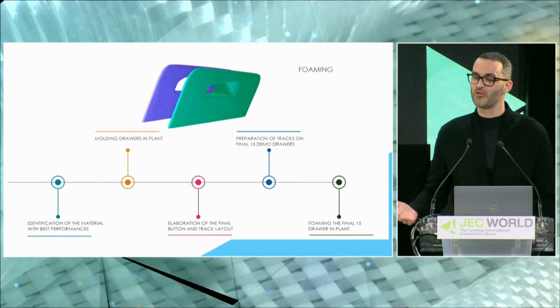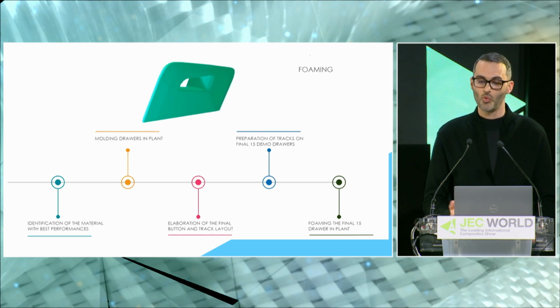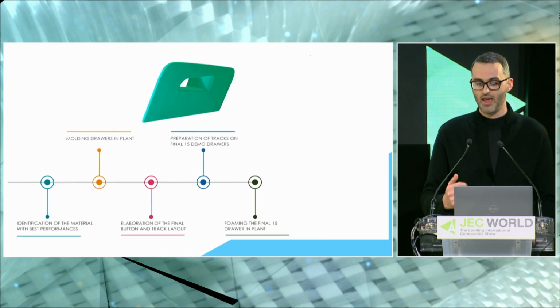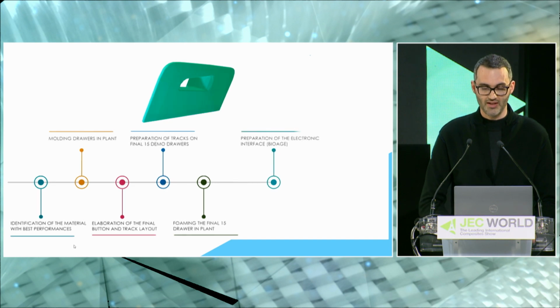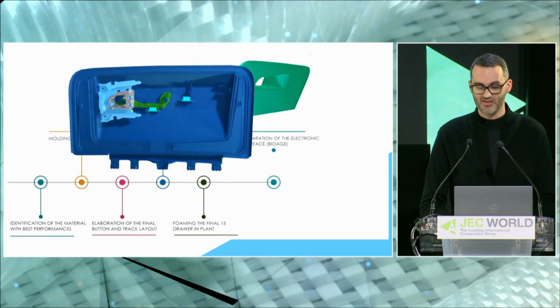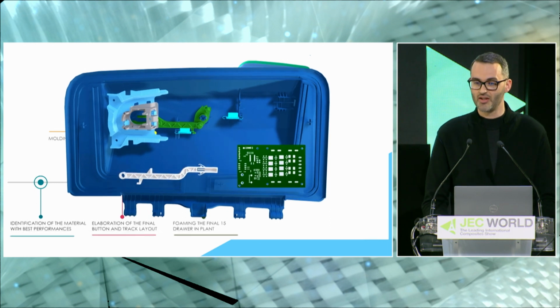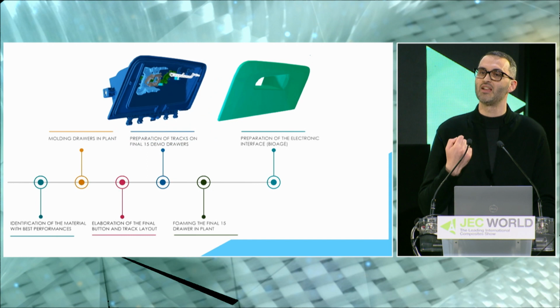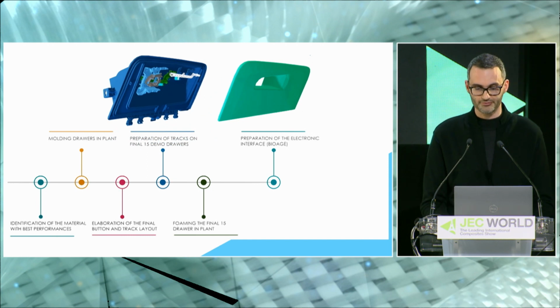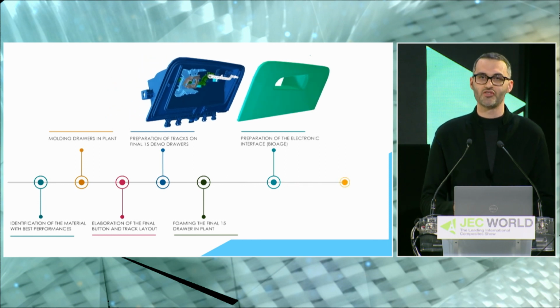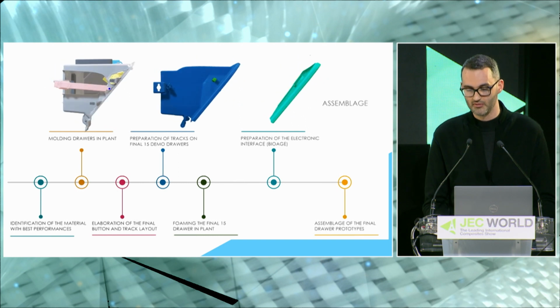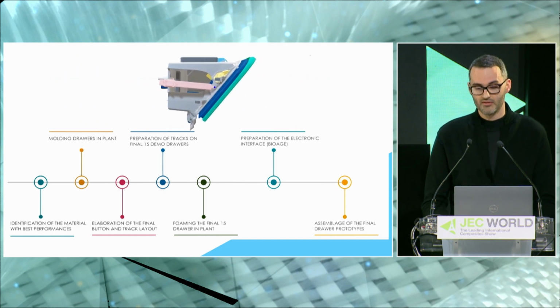And then we are moving to the other manufacturing phases that are typically performed on traditional materials. So we are foaming it in order to have an aesthetic surface, and this foaming is performed only on the aesthetic part. In the meantime, you also have to think about the electronics. The rear part of the drawer has electronics that you need to fit inside it. So there is an electronic circuit inside the component that enables the switch on, switch off that tells the CPU to open or close the drawer. And then there is the validation: first the completion of the manufacturing phase, so the assembly of the overall component, and then the validation phase in which you compare the component to the traditional one in order to be sure that the properties are exactly the same.